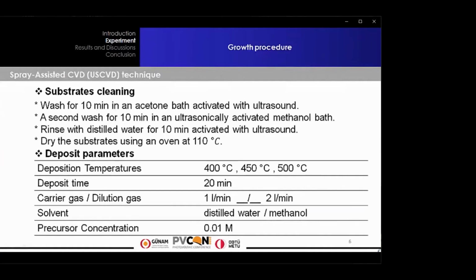First of all, the substrate is cleaned according to these steps. Wash 10 minutes in an acetone bath. Wash 10 minutes in a methanol bath. Rinse 10 minutes in a distilled water bath. Dry the substrate using an oven at 110 degrees Celsius.